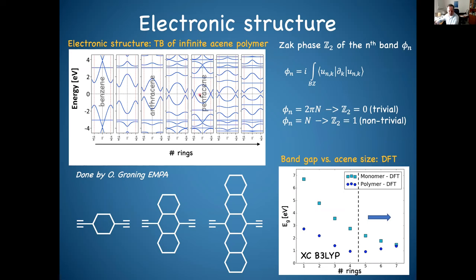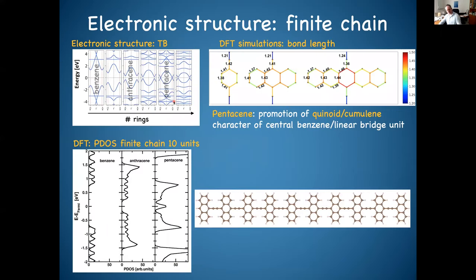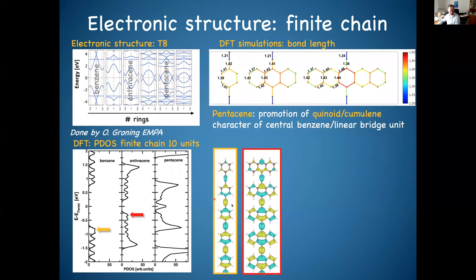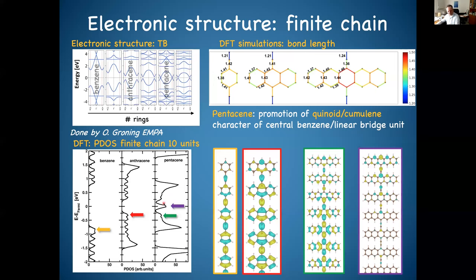DFT calculations confirm that when going from the anthracene to pentacene unit, there should be a closing band gap followed by reopening — a phase transition. In tight-binding calculations you can calculate the ZAK phase and confirm this is indeed a topological transition. DFT calculations on finite chains show that for the anthracene-based chain there is a band gap with delocalized states, while for the pentacene-based polymer, non-spin-polarized calculations reveal a state appearing in the middle of the band gap strongly localized on the edges.